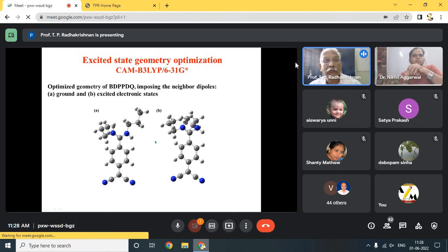But just as an aside, why do we fix this angle? For this, we did another modeling, for which I have not put any slides here, because it is a deviation from what we are talking about right now. We take the molecule in a simple molecular mechanics calculation and pack around it some 50 neighboring molecules from the crystal lattice structure. So now we have a central molecule surrounded by 40 or 50 neighboring molecules. Now we let this molecule's geometry rotate artificially by modifying this dihedral angle, and I can go on calculating the lattice energy.